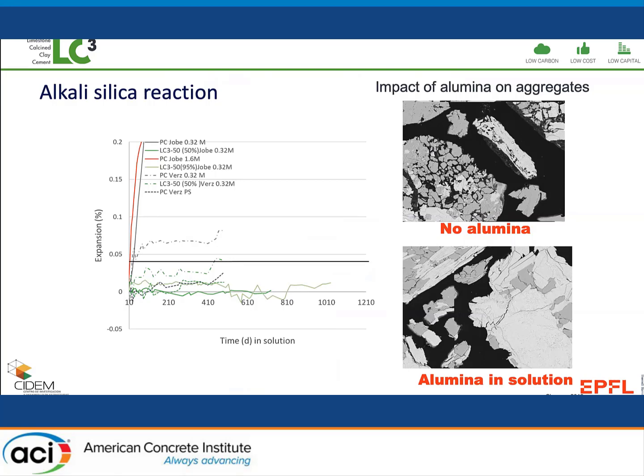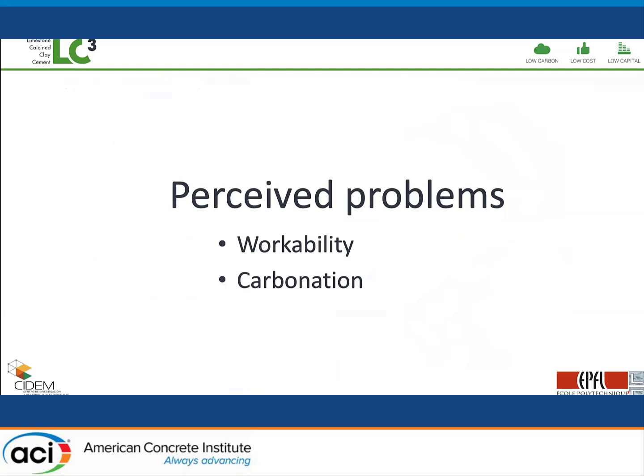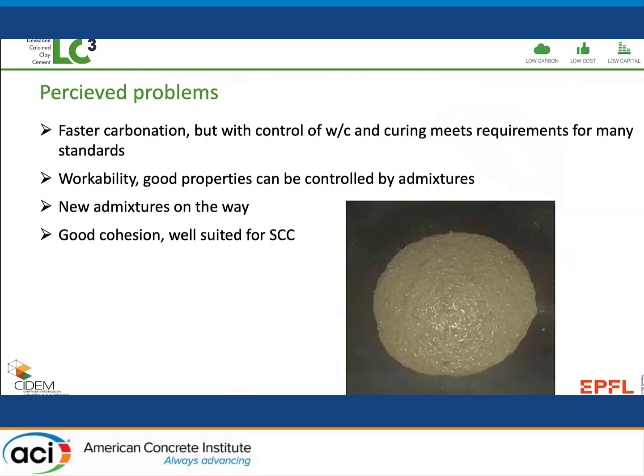Alkali silica reaction, very good because it brings down the alkalinity, but also because it releases alumina to the solution. And we know that a small amount of alumina in solution can drastically decrease the dissolution of silica. Now, the two things people go on about are workability. I've shown you many examples, and Jesper showed a nice example of how the workability can be really good. And in fact, if you want a self-compacting concrete, you actually may have a lower overall cost of admixtures because it's so resistant to any segregation or bleeding, you don't have to add any viscosifying agents.